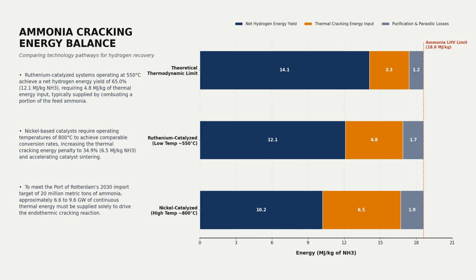Ammonia is the primary chemical carrier for transoceanic hydrogen transport. However, converting ammonia back into hydrogen gas imposes a severe thermodynamic penalty. Cracking is highly endothermic, requiring significant thermal energy inputs. Ruthenium-catalyzed systems operating at 550 degrees Celsius achieve a net hydrogen yield of 65%. This process requires 4.8 megajoules of thermal energy per kilogram of ammonia. This thermal energy is typically generated by burning a portion of the imported ammonia itself.